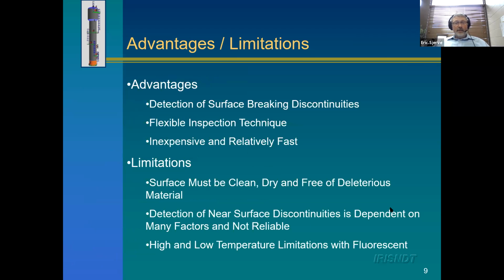And then this is the advantages and limitations. So with MPI, that's probably the most common technique you're going to see in Alberta. It's relatively cheap. It's fast. It can be done in all weather conditions. There's lots of people that are trained in it, and it's great at finding surface breaking defects. So it's used all the time for new fabrication, which is looking for defects that may be there in the welding process with new parts. And it's used all the time for in-service inspection. And that's things like looking for vibration to see if you have fatigue cracking. Limitations, you have to clean the surface. It's not going to find anything subsurface, and there's temperature limitations. So that's a quick summary on MPI. And like I say, that's probably the most common technique we see in Alberta.